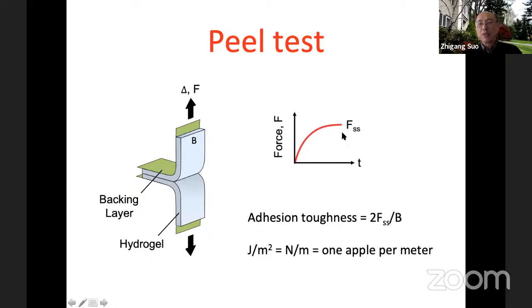This steady state force measures adhesion energy. What you do is divide the steady state force by the width of the sample. This becomes energy per meter squared—it's just Newton per meter. For people who don't have a sense of the number, 1 Newton is just the weight of 1 apple. So you need to distribute the weight over 1 meter long. That's not a very large force—tiny force, very brittle—or 1 joule per meter squared. All right, so that was the standard when we started at that time.